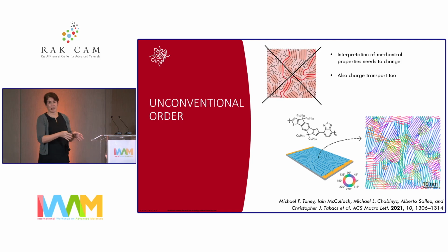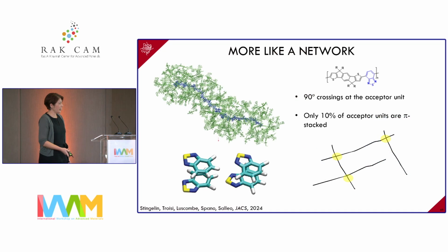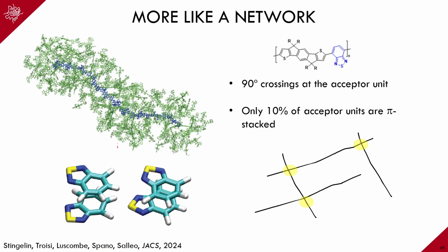So given that this is now the morphology that we have, well, how do charges actually move through these different types of materials? If we have a different microstructure, we need a different model for charge transport too. So here we collaborated with additional people doing MD simulations. And what MD simulations confirmed was what we were thinking, which is that these polymers are extremely linear, and all these side chains are really covering up that linear backbone.